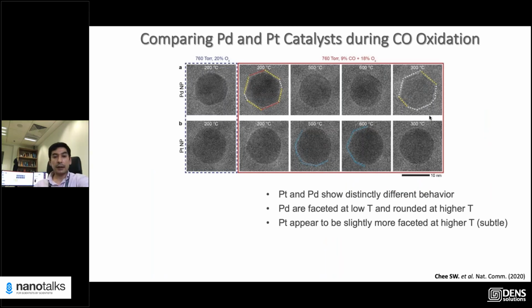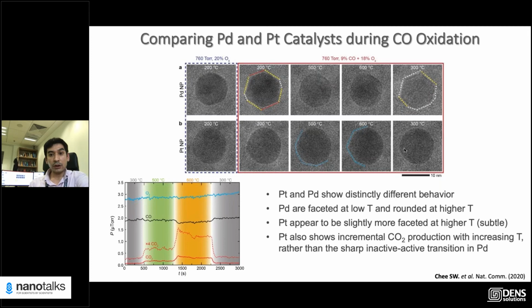We did the same experiment with platinum, just to compare with the palladium. In the platinum experiments, the changes were subtle. If you look at the output, the platinum gives you a very subtle change in the production of CO2, and consistently the structural changes in the platinum were also not as vivid as in the case of the palladium, right? In the case of the palladium, you have a really drastic change going from here to here, and correspondingly, the activity of the reaction was high.